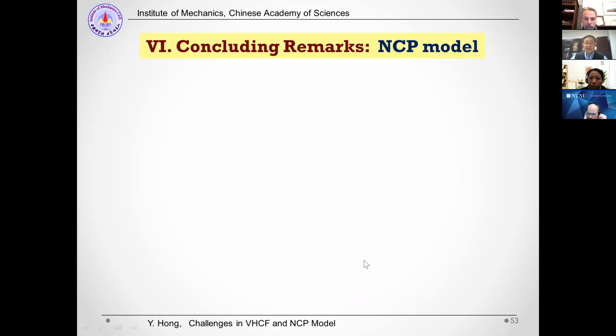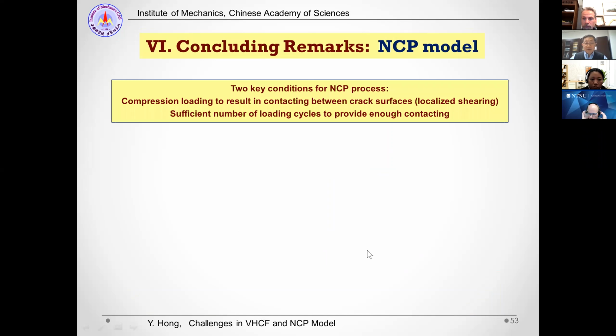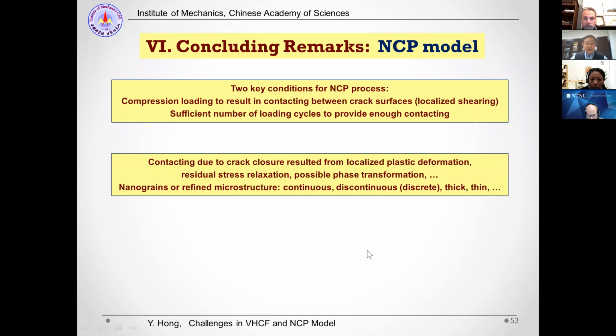The third concluding remark is the NCP model. There are two conditions for the NCP model or NCP process. The first one is that compression loading should be maintained. The second one is a sufficient number of loading cycles. This process is related to crack closure. It results from localized plastic deformation, residual stress, and phase transformation. The formation of nanograins and refined microstructure can be continuous or discontinuous, and the thickness can be large or small. It depends on the materials and loading conditions.